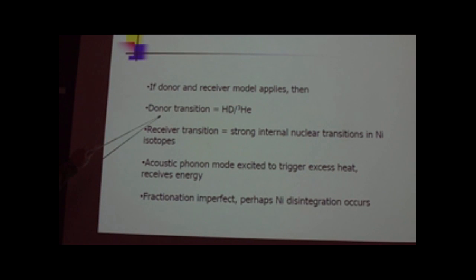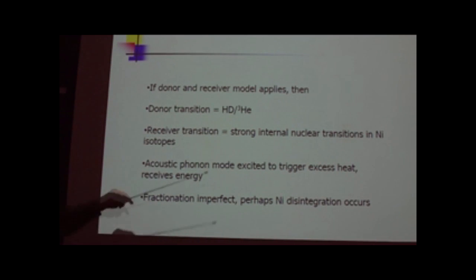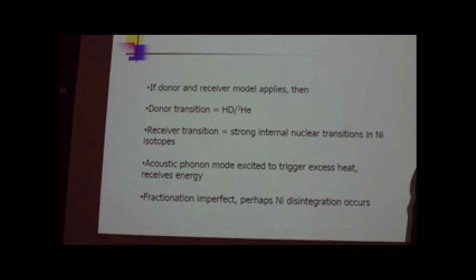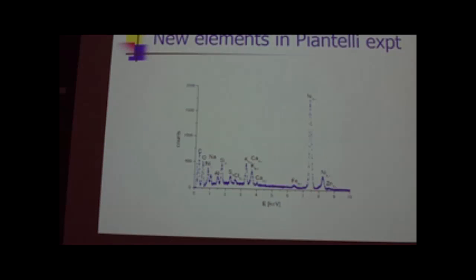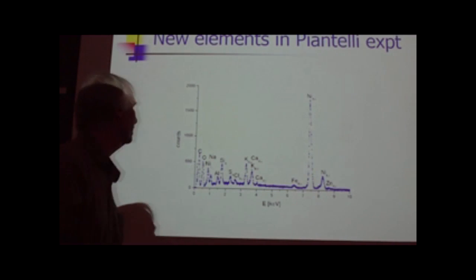The donor-receiver mode applies. We'd expect the donor transition to be HD going to helium-3. The receiver transition would be nickel, with acoustic mode phonon excitation. We drove the acoustic phonon modes, and that's where the energy should go in this. The fractionation in the nickel is imperfect. And so I'm thinking that gives the possibility within the model of basically accessing unstable states in the nickel and leading to disintegration. Now in Piantelli's experiment,